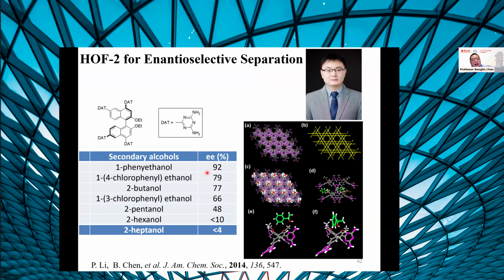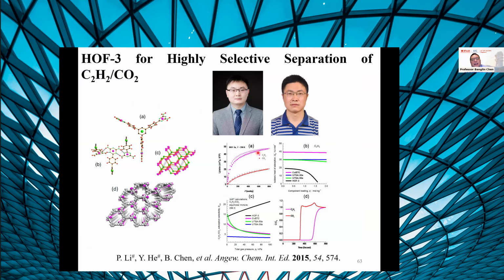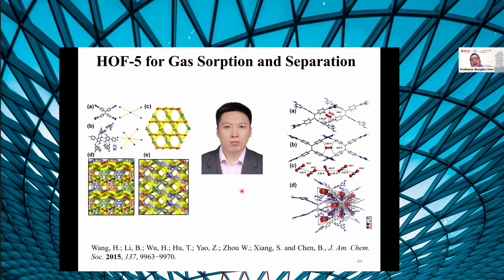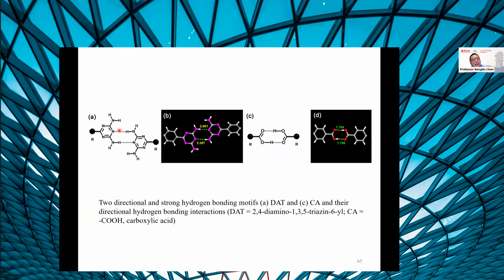For example, this for high chiral separations, and the separation performance actually is quite good. And for different kind of gas separation, acetylene, carbon dioxide, and also carbon dioxide capture. However, for this kind of organic linker, typically it will form different kind of isomer, and also synthesis comparatively is not so straightforward. So we have been wondering to use very famous carboxylic acid to construct HOF material. And furthermore, this kind of carboxylate easily form this kind of dimer. So the HOF structures are kind of predictable. And gradually we made some progress.